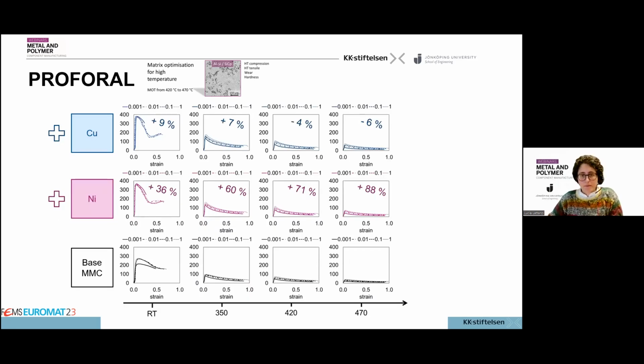We performed mechanical tests, as said, on all the materials. Now I'm presenting the results of compression testing at elevated temperature. So we went from room temperature and then we tested at 350, 420, which is the current maximum operating temperature, and then 470. And we saw clearly, first of all, also the effect of strain rate, but we can see clearly the effect of chemical composition in the matrix.